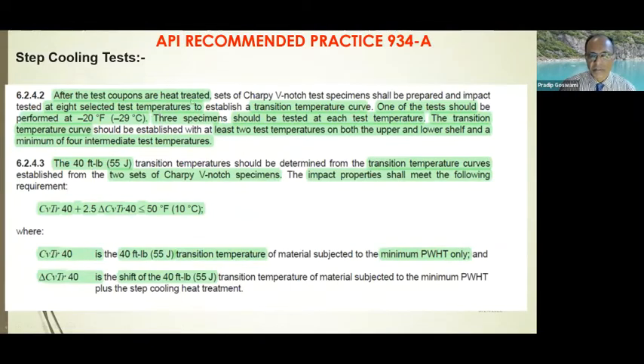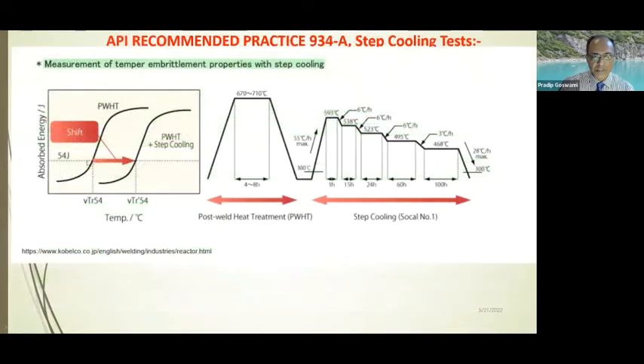Typically 8 selected test temperatures are used. You do a Charpy impact test to establish the impact test temperature curves. When you start with a higher temperature, you have a higher absorbed energy. As the temperature falls, the impact values go down, and that's the way you develop the curve without step cooling. But of course, following the post-weld heat treatment and step cooling, you have to do another set of impact tests to establish the transition curve.